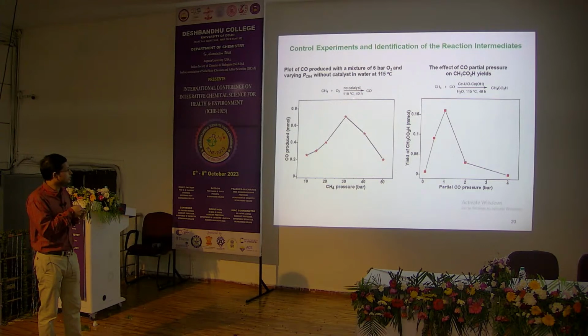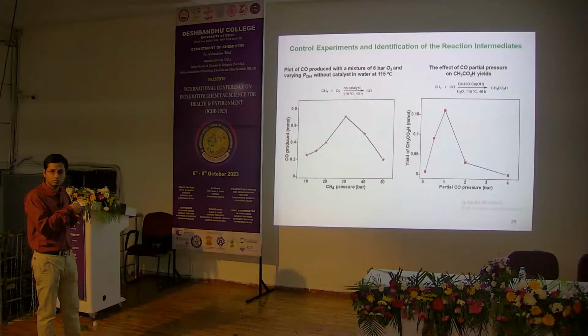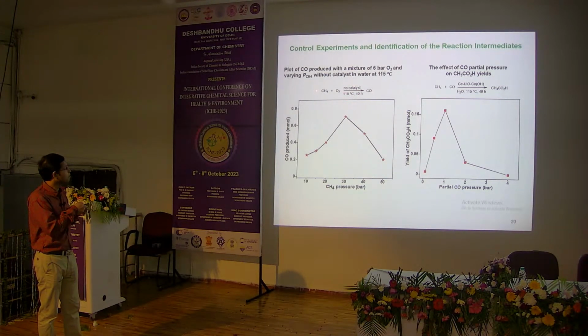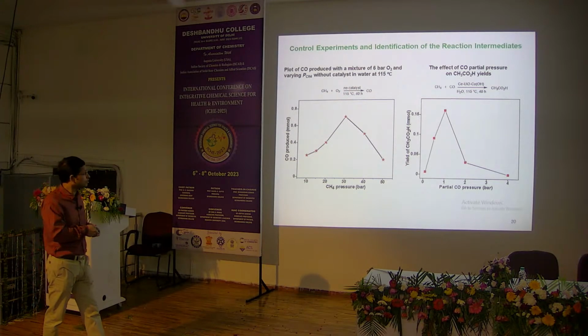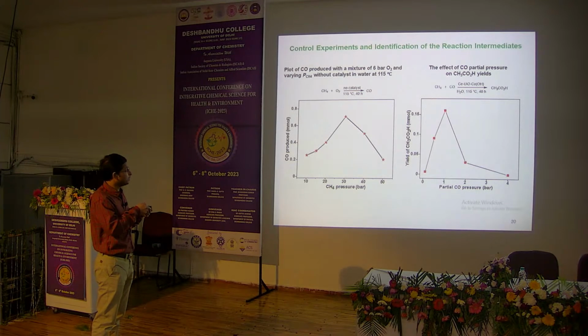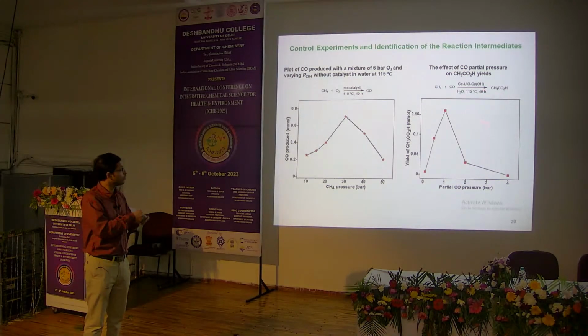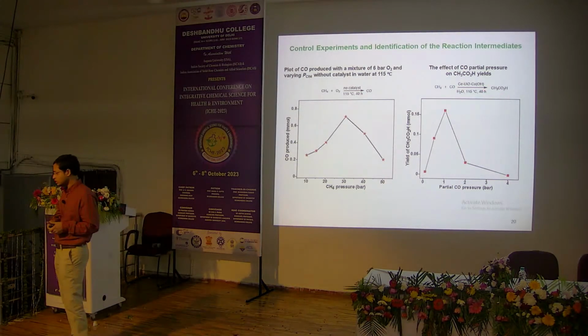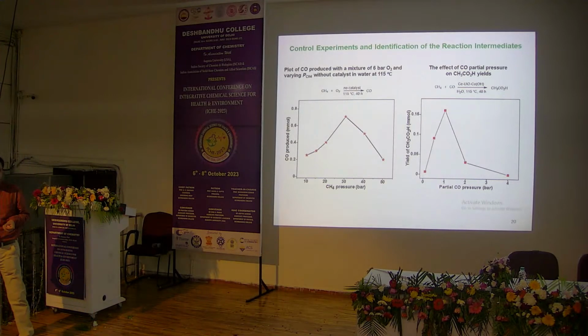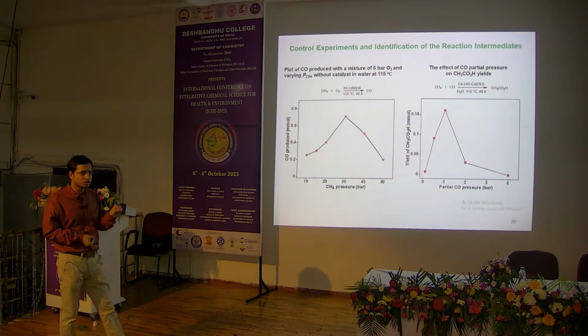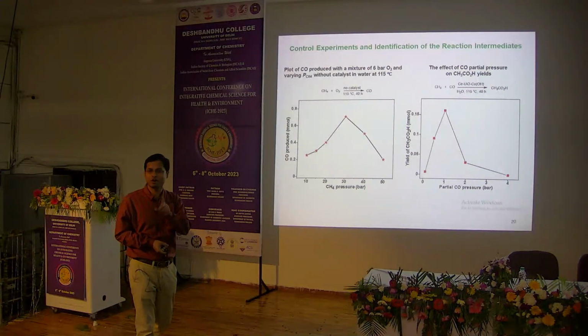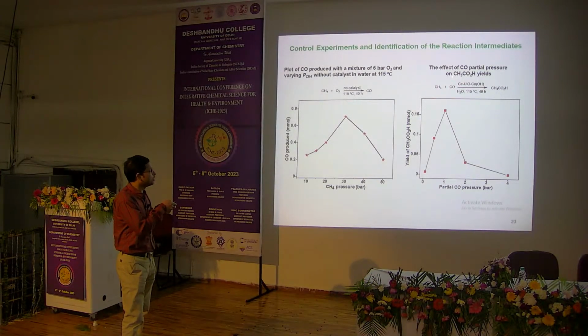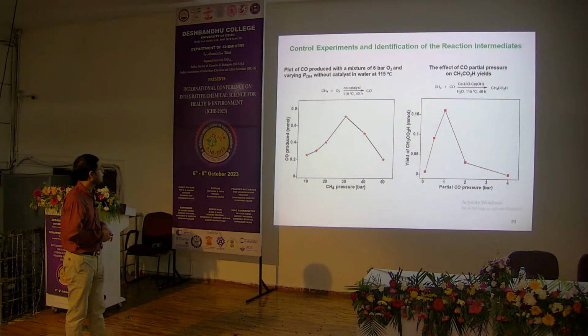If you do the catalysis in the identical reaction conditions of the optimized conditions, but with no catalyst, and you just heat the methane and oxygen, we get CO. And not only that, if you do methane and CO, we get acetic acid, even without oxygen. So this indicates that most likely in the optimized reaction condition, some amount of CO is produced by the reaction of methane and oxygen,